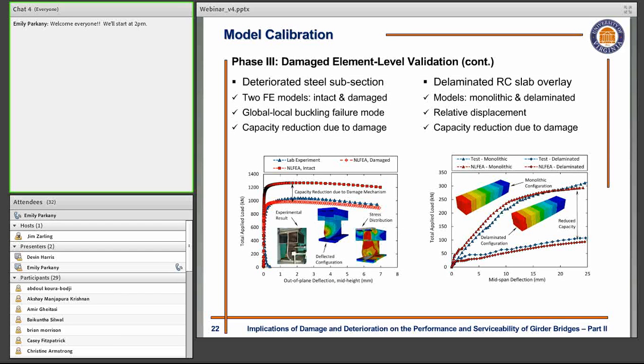For each of these cases, we actually developed two numerical models, one with the intact configuration and the other with the damaged configuration. We performed the same type of numerical analysis on those and tried to validate them by comparing the results from these numerical investigations to the experimental data. In the case of the corroded steel girder, as you can see in the left figure, our model was able to predict the behavior of the system in the elastic region and also the ultimate capacity and softening stage. Other than that, the model was able to capture the failure mode of the system, which was governed by global local buckling, buckling of the web plate at the middle height of the web.